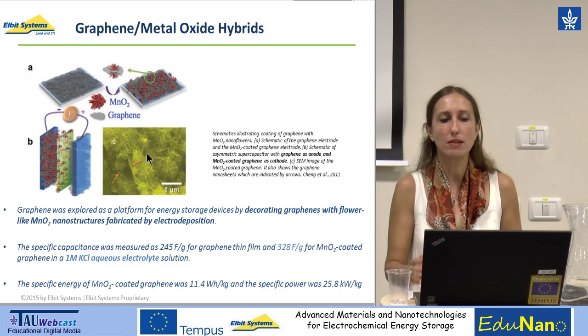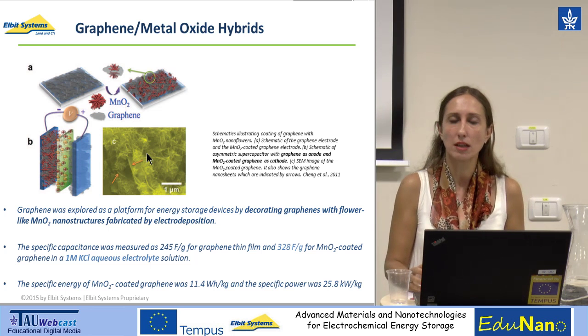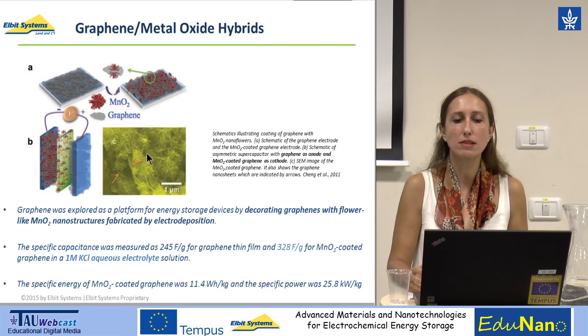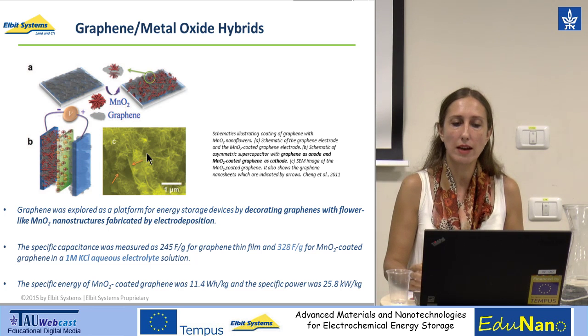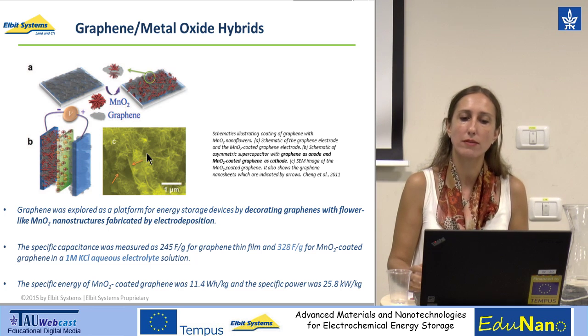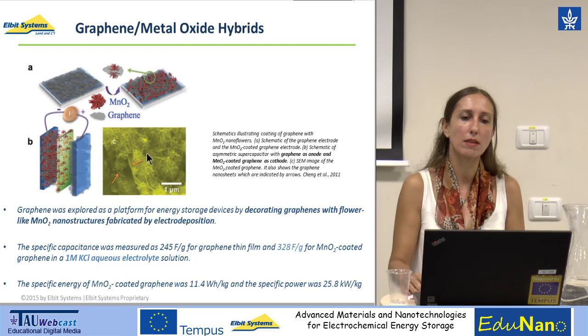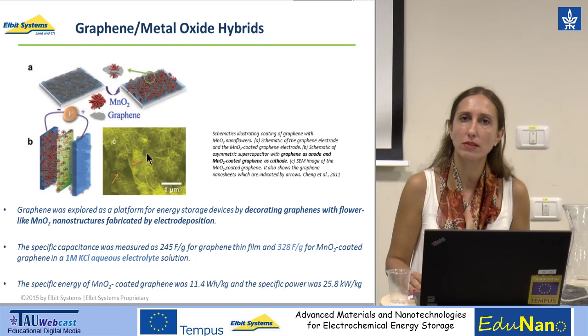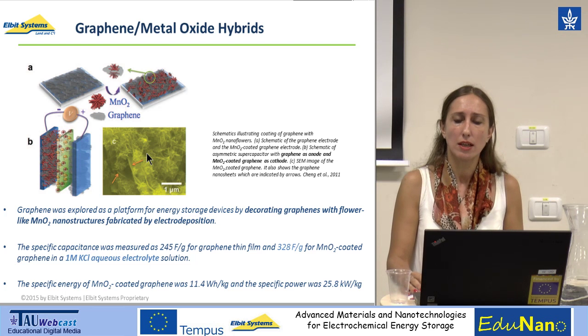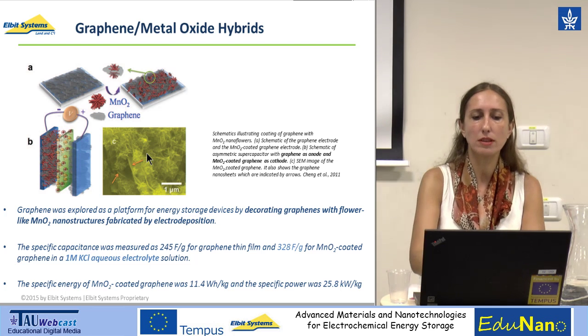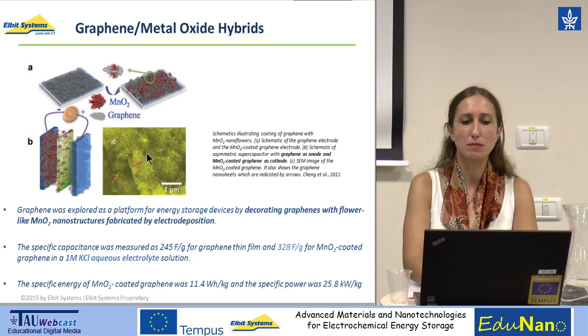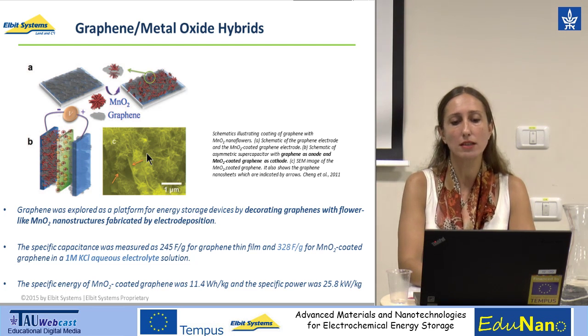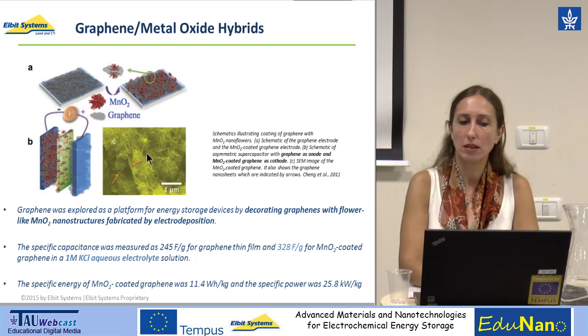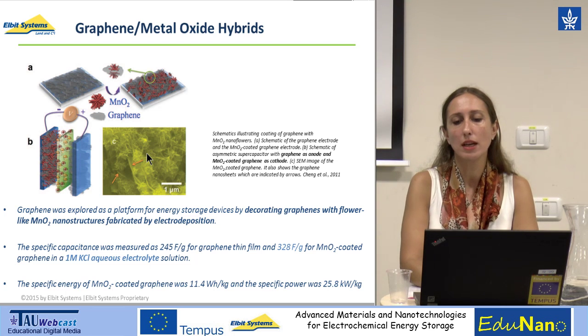The specific capacitance was measured in a neutral aqueous electrolyte, potassium chloride, 1 molar electrolyte solution, and what they have attained is 245 farad per gram for graphene thin film, and with the coupling of the manganese oxide decorated graphene cathode, the capacitance increased to 328 farad per gram, a very nice number. If you translate that number to the specific energy of manganese oxide coated graphene, we attained 11.4 watt-hour per kilogram, and the specific power was 25.8 kilowatt per kilogram.